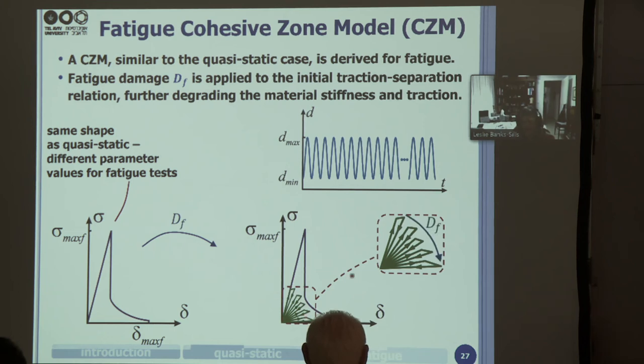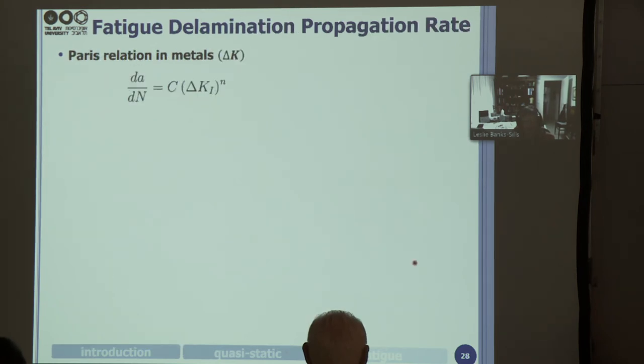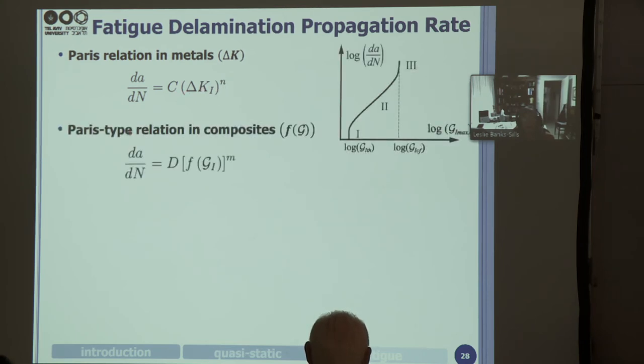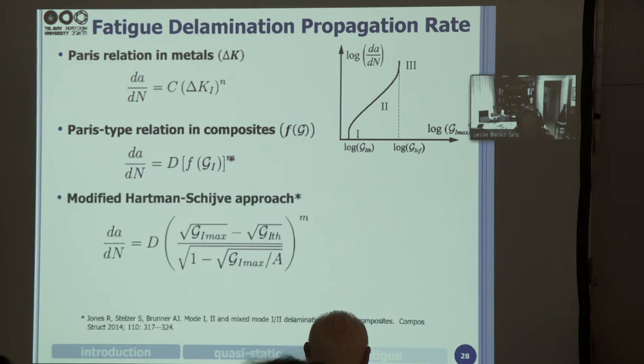And we have to find parameters that are applicable for this fatigue cohesive zone model. So in addition, I remind you of Paris's law, where da/dN is a constant times delta K to the power n. And we're using a Paris-type relation here, where we have the Paris constants D and m. But now for a function of G, we use a modified Hartman-Schijve approach, which was published in the paper noted below, where we have the square root of G1 max in the cycle. We find the square root of G1 threshold, and we also find this parameter A.